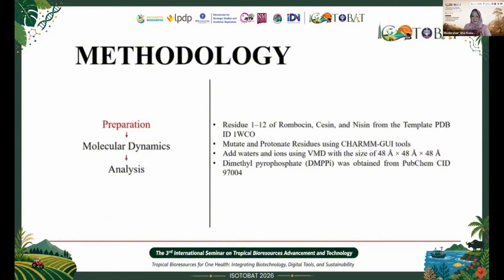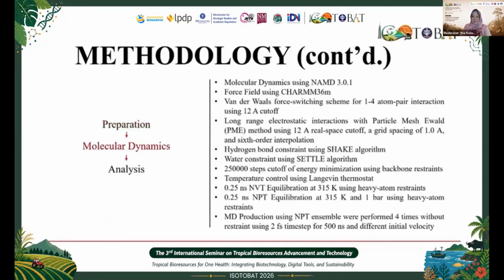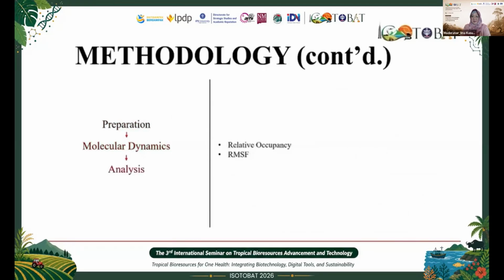This study employed three steps. First, structure preparation: peptides were taken from 1WCO, and Cesin and Rombocin were mutated using CHARMM-GUI. Water and ions were then added using VMD with a size of 48 angstroms in every direction. DMPPi were then added 15 angstroms from the peptide center of mass to increase the odds of interaction. After the system is ready, we run molecular dynamics in NAMD using the CHARMM36m force field for 500 nanoseconds, 4 times. Then, we conduct relative occupancy and RMSF analysis.